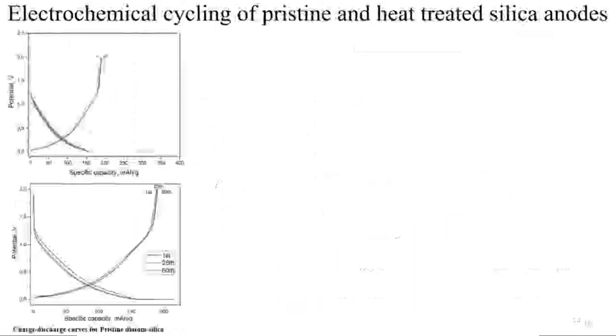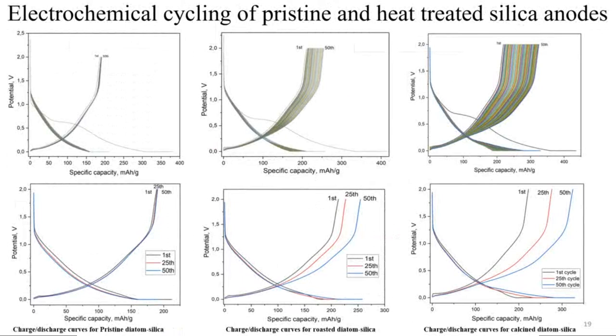We see an increase in the specific capacity for the silica anodes because of the lithiation mechanism in silica-based anodes. From the literature, when silica reacts with lithium, it acts as a convertible oxide, which leads to irreversible phases like lithium oxide, lithium silicate, and electroactive silicon domains. It is these silicon domains that react further with the lithium to increase the capacity. And that's what we see for the silica-based anodes. Okay.